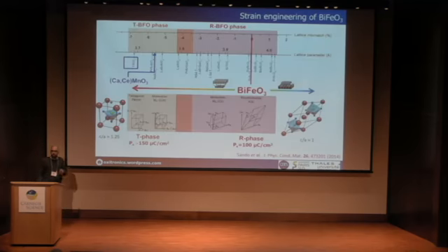As a ferroelectric material, we chose bismuth ferrite, and you heard a lot about bismuth ferrite, especially yesterday. This material can be stabilized in another phase, called the T phase, by high compressive strain. In this T phase, the polarization can be even bigger than in the bulk. We fabricated thin films of this T-phase BFO using yttrium aluminate substrates and a calcium cerium manganite buffer electrode. The films were grown by pulsed laser deposition.